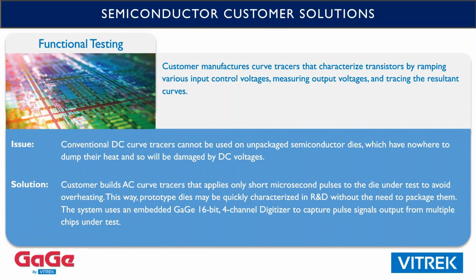So rather than forcing the researchers in R&D to go to the trouble of packaging their chips, what this customer does is makes a curve tracer that only applies a very short pulse instead of DC voltages. So it might apply a pulse of a microsecond or two every millisecond, thereby reducing the power that's applied to the die by a factor of 1,000 to where it doesn't overheat. So they can measure the same curve tracer curves, except without overheating and burning the die. So for that they embed our digitizer within the instrument that they sell, and they need 4. I believe each one needs at least 2 channels, so I think it's 2 channels times 2.